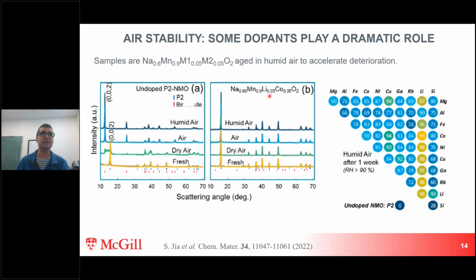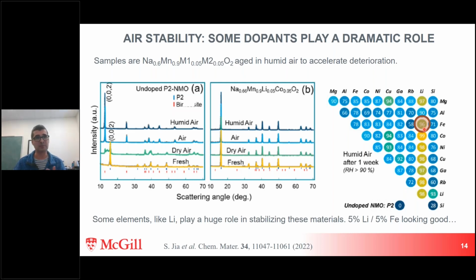And if we put 5% lithium, and in this case, 5% cobalt, but there are a number of co-dopants with lithium that keep the original phase at 99%. So undoped was 0%, and then we put 5% lithium, and we get 99% of that original phase. So we've really dramatically improved the air stability of these materials with a very small amount of doping. Okay, so some elements like lithium play a huge role in stabilizing these materials. So for example, 5% lithium and 5% iron looks really, really good. So on the theme of trying to get sodium, iron, manganese to work, we're getting close. We're doing some really good stuff.